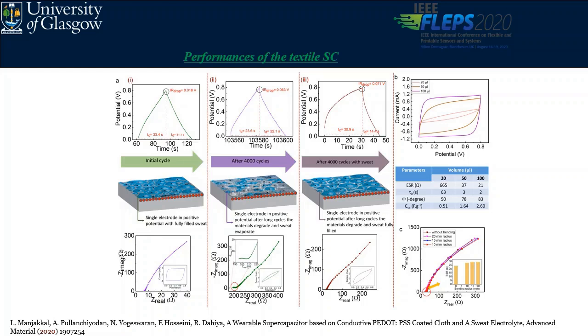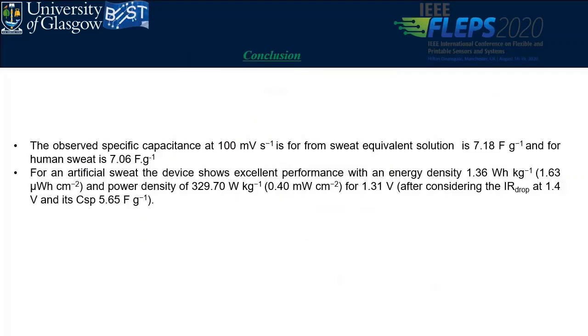And you can see here the comparison of performance for different volumes, and also bending radius. I observed almost similar performance. And this is the conclusion. At almost 100 millivolt per second, I got 7.18 farad per gram, and the energy density is almost 1.36 watt hour per kilogram, and it is almost the same performance with the electrolyte.